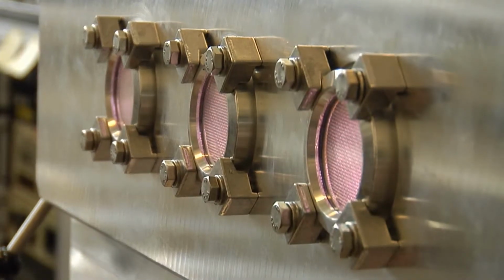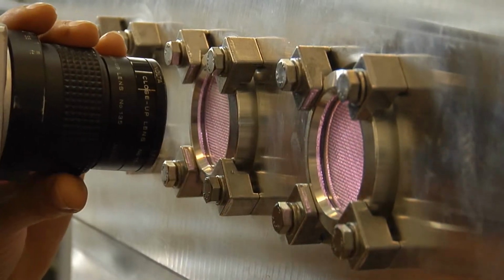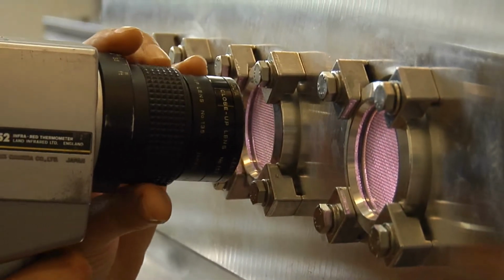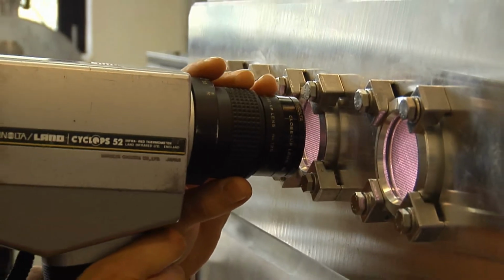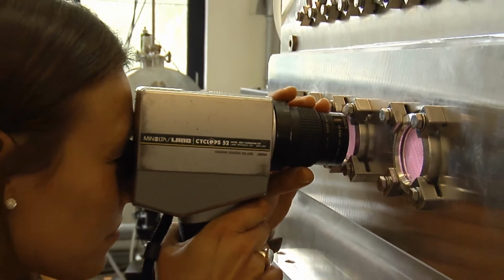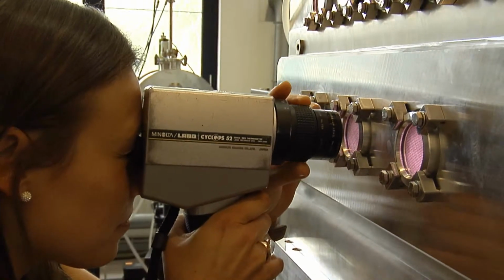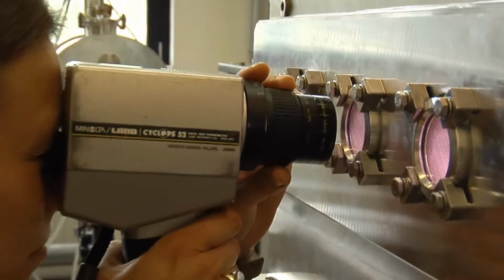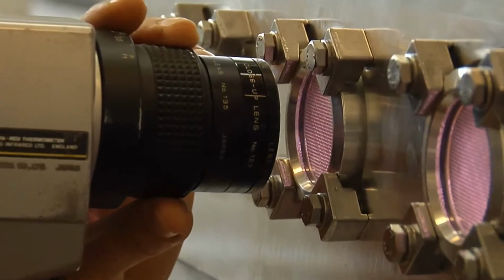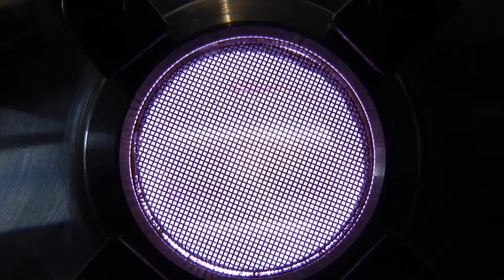And so what we're interested in is really what is the flux of the atoms and chemical species in the gas phase to the diamond surface that enables us to grow diamond as opposed to other forms of carbon, such as the more stable graphite. So one of the areas that we've been researching heavily for the last several decades has been the composition of these, what we call plasmas, that can generate the radicals and the atomic species necessary for growing diamond.